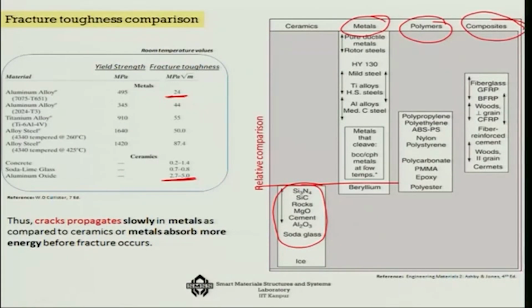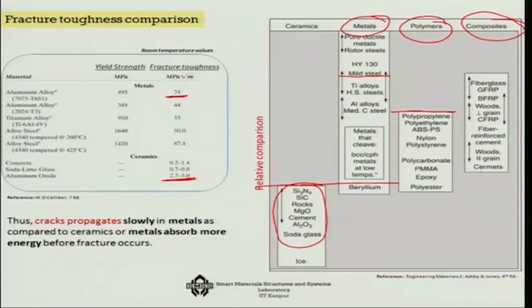One can say that just by shutting eyes itself. And among the metals, of course, there are variations; mild steel has a higher fracture toughness than aluminum alloys. Among the polymers, even though they can sustain a much higher strain, their modulus of elasticity and yield strength being low, you will not get a fracture toughness beyond a certain value. And with composites, you will get a kind of mixing of these possibilities. You can have metal ceramic composites, where the metal has a high fracture toughness and the ceramic brings it down a little bit, and polymer ceramic composites, where the polymer has slightly higher fracture toughness and the ceramic brings it down, so you get some kind of average value. So, that is the fracture toughness comparison of various types of material.